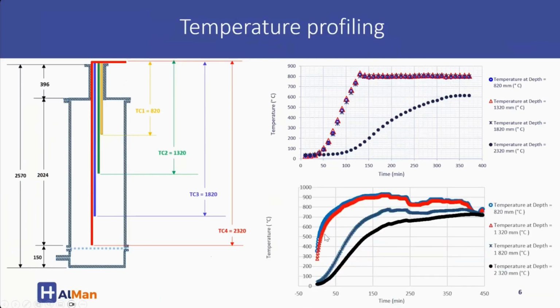To improve this lag in temperature, we increased the amount of material in the retort so we could cover the first two thermocouples, while the others were exposed to the atmosphere in the retort. To minimize the lag, we made sure to overshoot the furnace temperature so these could catch up quickly.